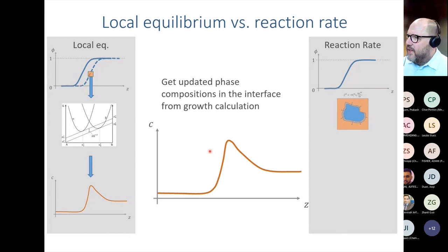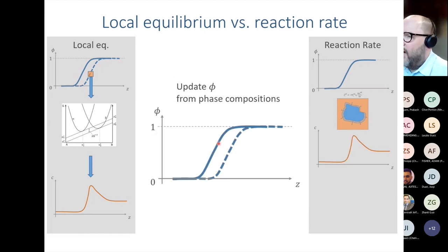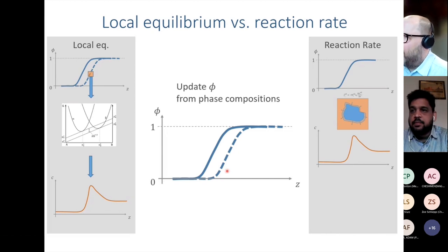Once we've got that, we now have an updated composition profile for any point in the interface. And once we have the composition profile, we can use that in order to update the order parameter. So the order parameter is following the composition profile rather than leading it.